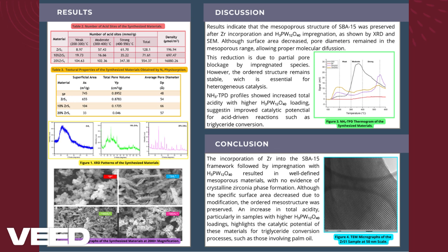SEM micrographs, Figure 2, reveal morphological differences. SP shows irregular, agglomerated particles typical of SBA-15. ZR-S1 displays fibrillar or rod-like structures. 10% ZR-S1 maintains dispersed fibrillar particles, whereas 20% ZR-S1 shows larger, more agglomerated particles, reflecting phosphotungstic acid accumulation.